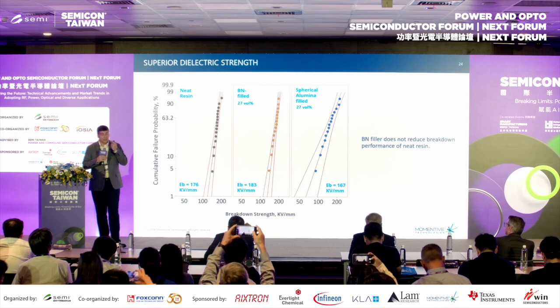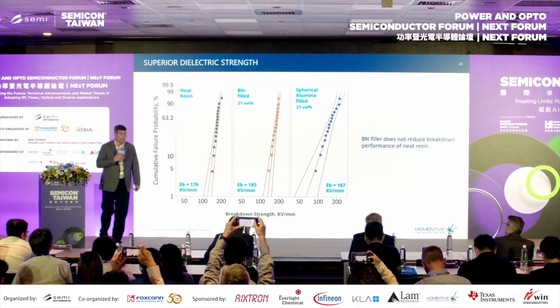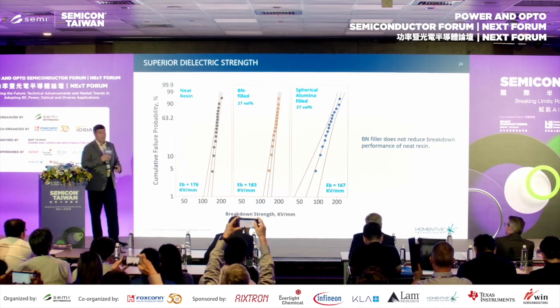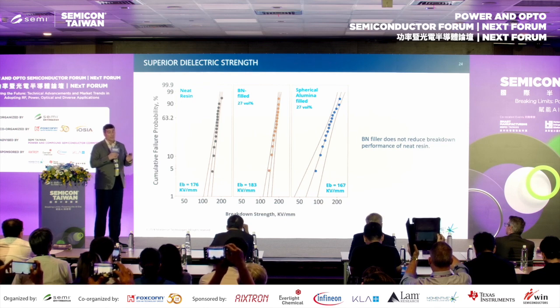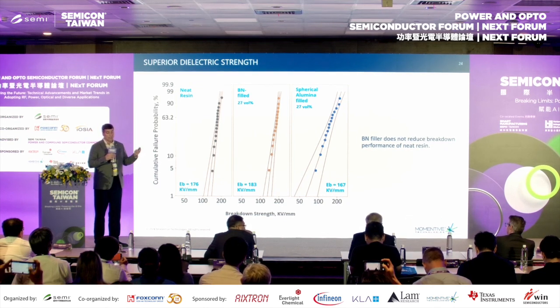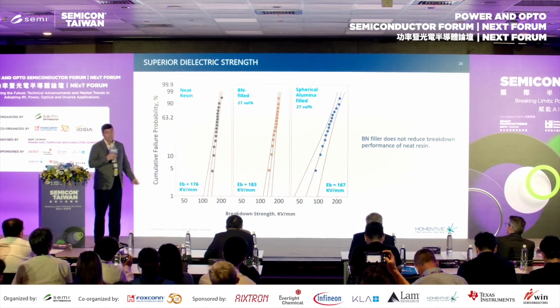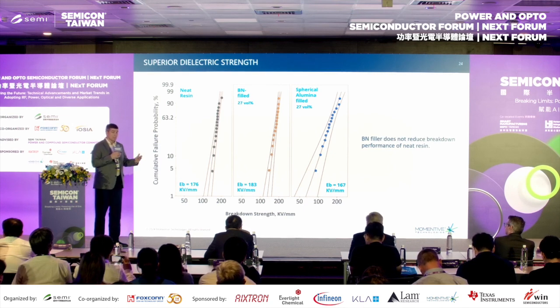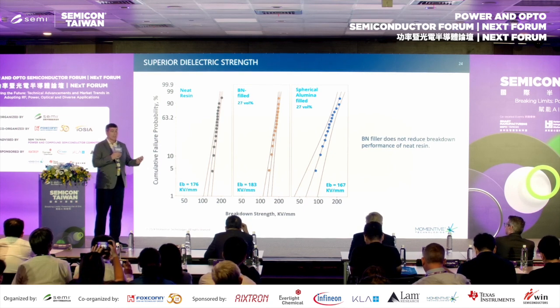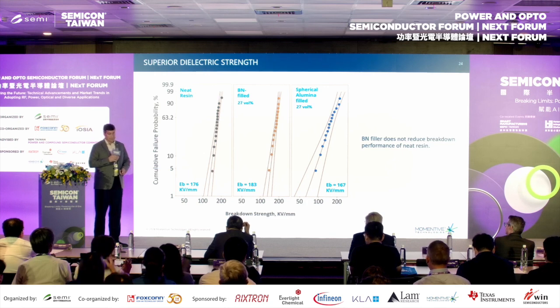As far as dielectric strength, again, BN is a very pure compound, so it has very good dielectric strength, and again, doesn't affect the breakdown voltage of the neat resin. So you're basically holding to that, whereas the spherical alumina tends to drop a little bit because of some of the other impurities that it tends to bring along.